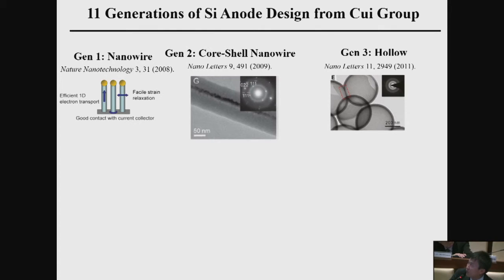So after these three generations, about 3 years of research, you recognize if you make a structure small enough, they will not break anymore. This looks easy. If you go to nanostructure, they will not be broken. However, the second problem is so hard to address. That is, every time you put lithium in, there will be volume expansion. Expansion will go towards the outside, pushing the electrolyte. So once you take lithium out, they're going to shrink. So you don't have an interface to build a so-called solid electrolyte interface. So your battery will also die with cycling. You cannot go for 500 cycles for your cell phone. You cannot go to 3,000 cycles for your electric car.